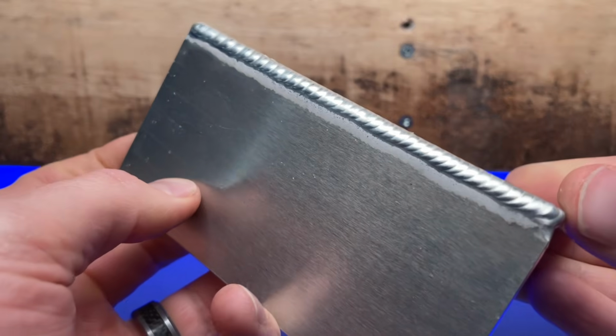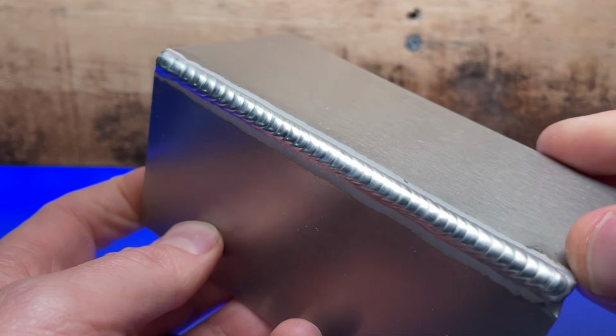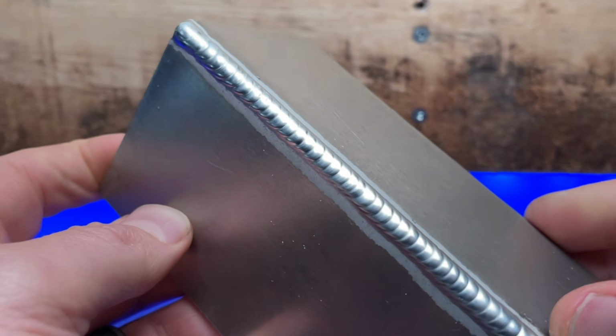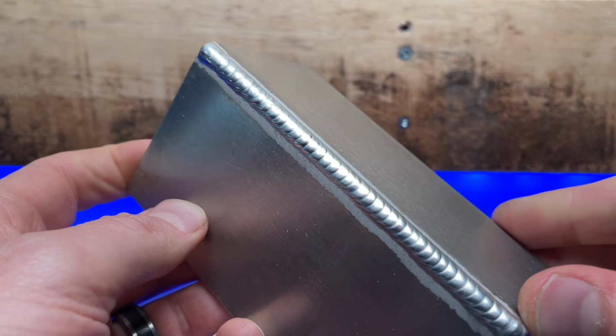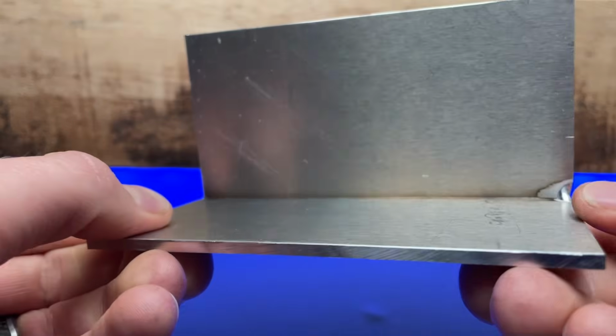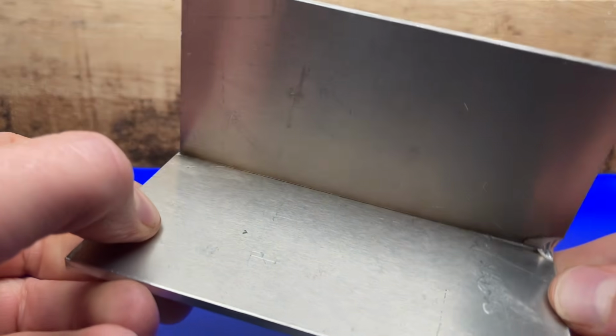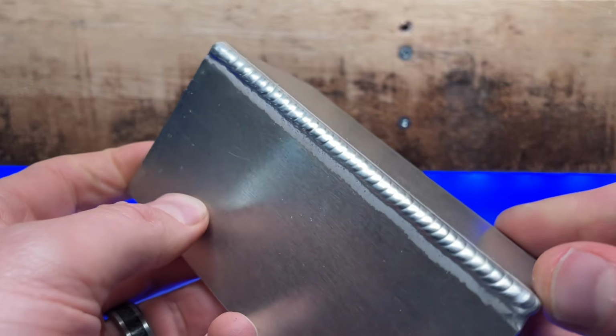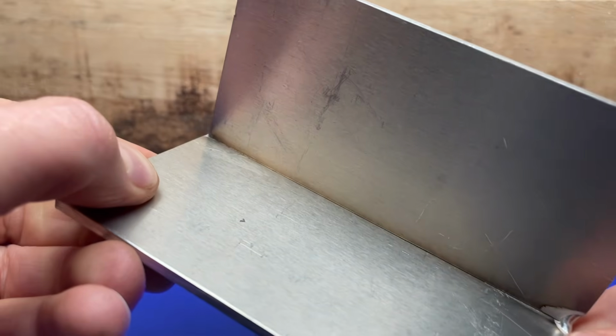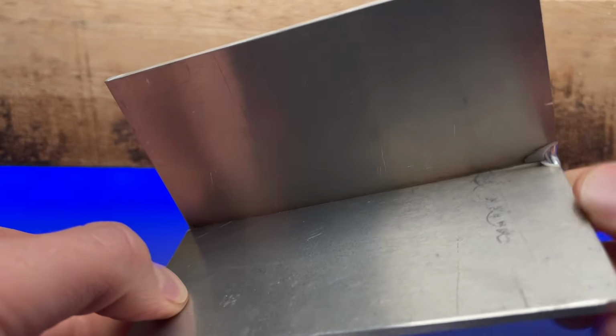Now let's compare bad fusion to proper fusion in real welds. Take a look at this outside corner joint being welded here. When it's all done, we can see that things do look pretty good. The cool thing about outside corner joints is they're pretty easy to inspect. Flipping it over though, we can see there is no penetration on the other side. Bummer, dude. The appearance of that one fooled us, man. Even though again, the weld looks pretty good, there's a lack of true fusion into the other side. This can be because one of the variables that we already talked about is off in some way.